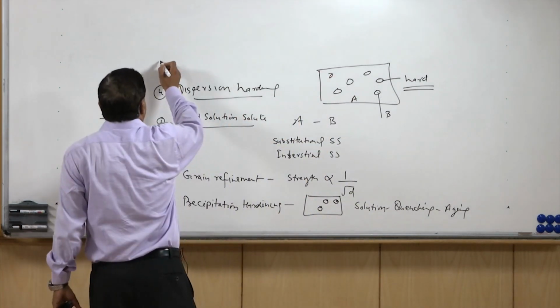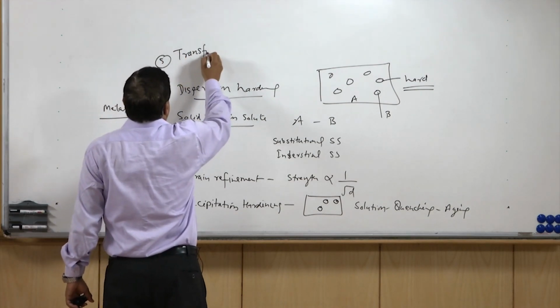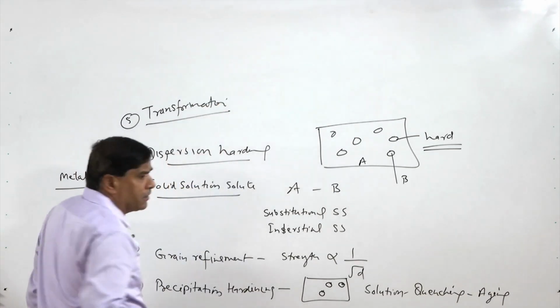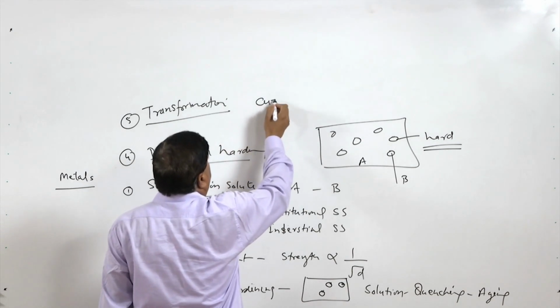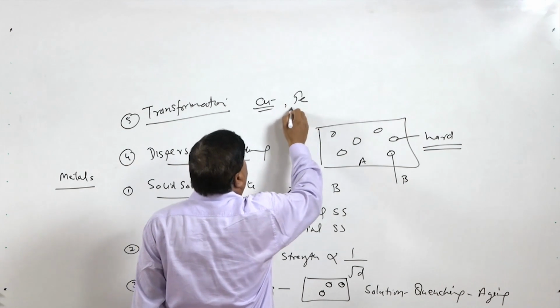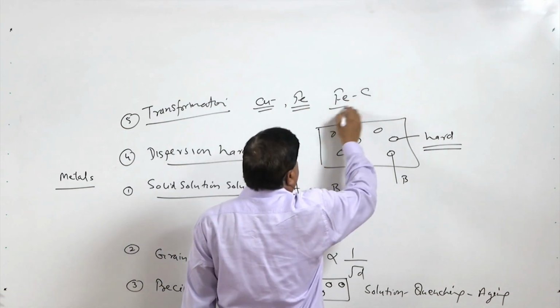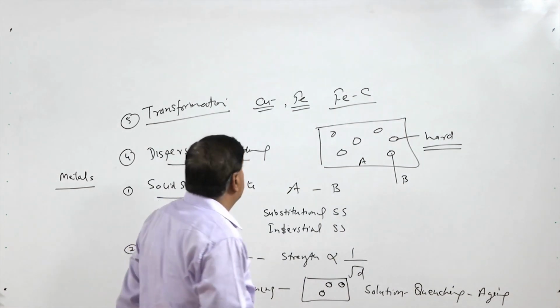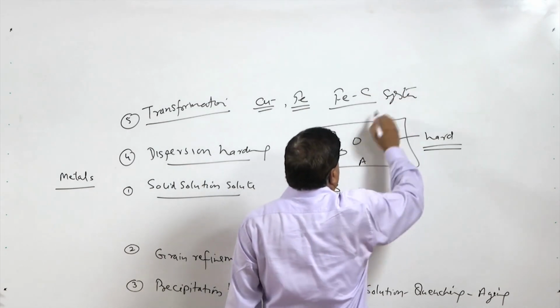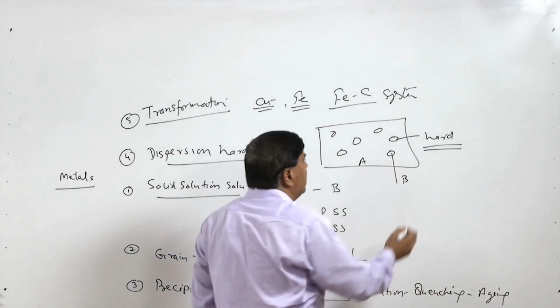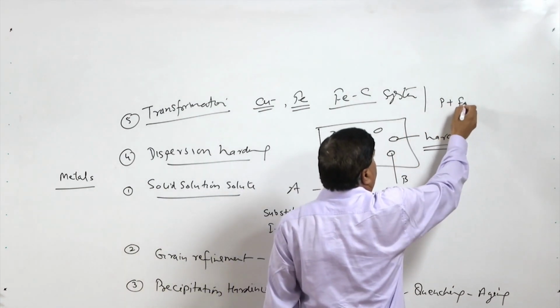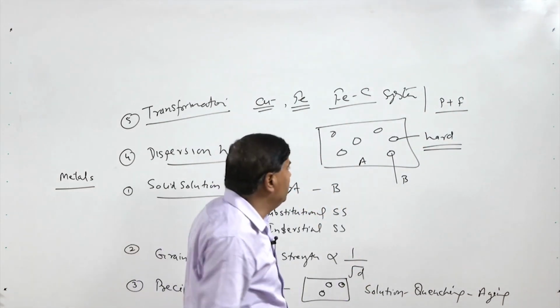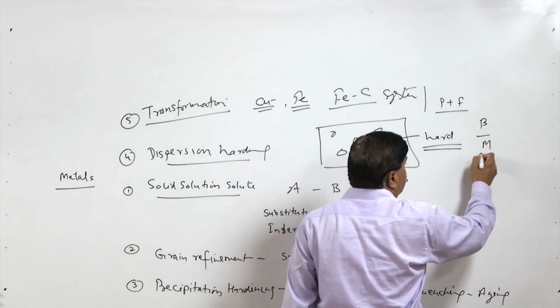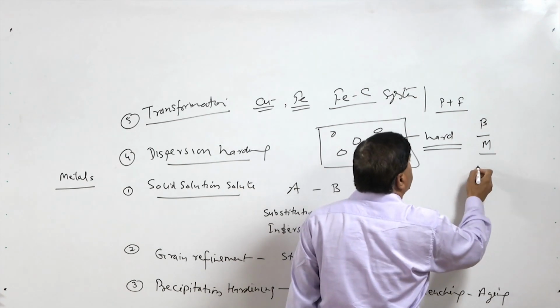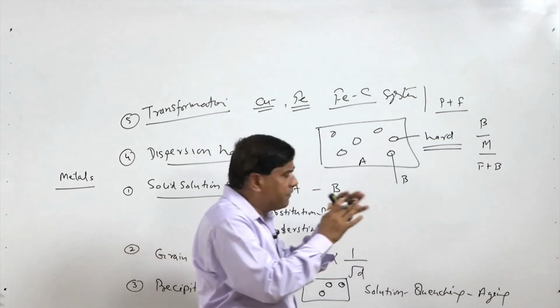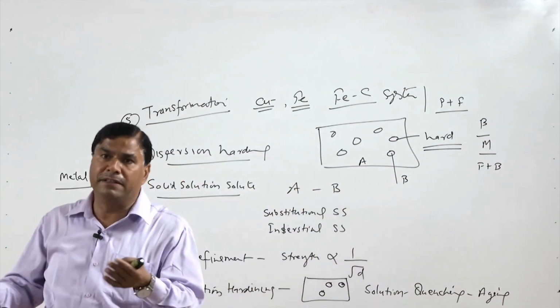heat. And the fifth one is transformation hardening, transformation hardened metals. These are mostly, say, copper based alloys, or mostly iron based alloys. So, we know that iron carbon systems form steel or cast irons as per the concentration. These systems result in the formation of different types of phases, like in normal carbon steels we will find pearlite and ferrite, but when they are subjected to specific kinds of heating and cooling cycles, we may have bainite, we may have martensite, we may have a very fine mixture of ferrite and bainite, etc. So, various phases can be formed which will have their own characteristics, and accordingly the properties will be affected.